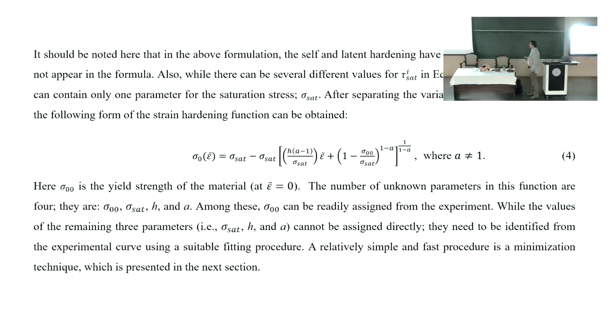Now we have the strain, equivalent strain, as the main parameter. As a function of that, we get the stress response of the material, and we have 4 parameters: saturation stress, initial stress when epsilon is 0. This is 0, then we get actually that sigma 0,0 is equal to sigma 0. So this is the yield stress of the material at 0 strain here.